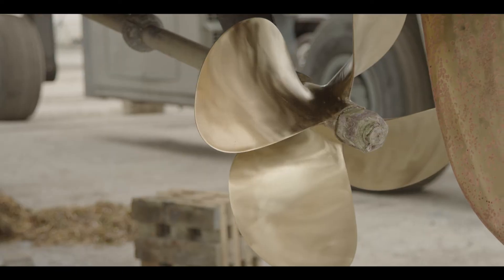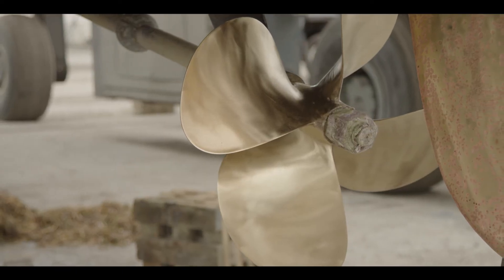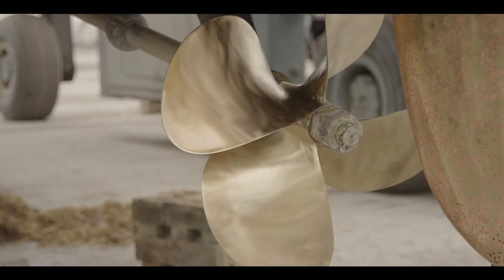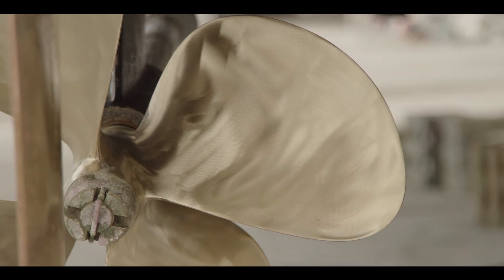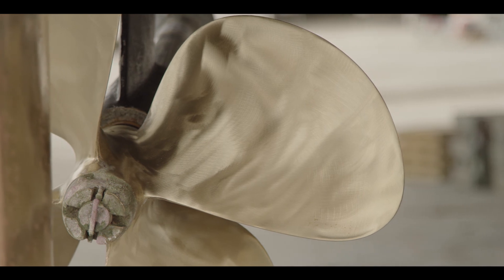Allow the propeller to sit and cure for a minimum of eight hours before launching or submerging in water. When GlideCoat PropOptimizer has been properly applied, the prop surface will have a shiny appearance and feel smooth to the touch.